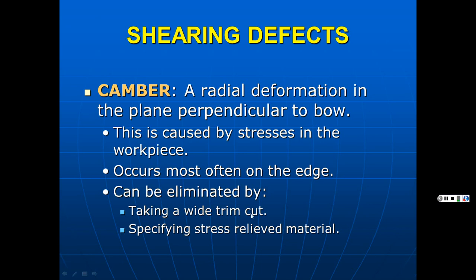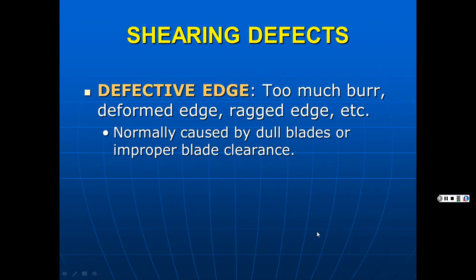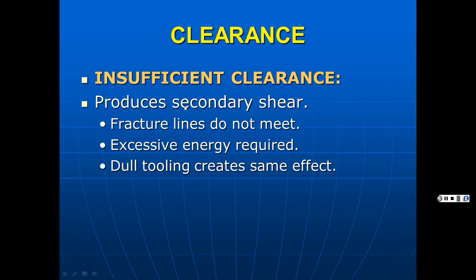Camber occurs most often on the edge, and can be eliminated by taking a wide trim cut, specifying stress relief material as well for the metal. And then a defective edge: too much burr, a deformed edge, ragged edge. So you get a rough edge of some type. That's a defective edge, normally caused by dull blades or improper blade clearances again. If you have insufficient clearance, it produces a secondary shear because it's trying to cut it, it can't, so then it smashes it again.